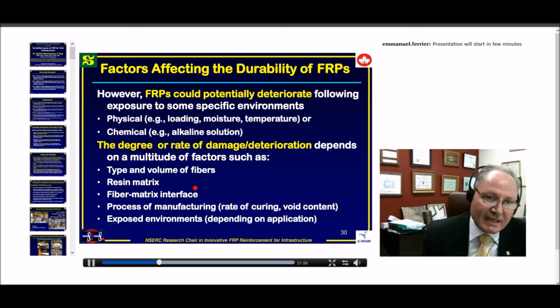I can tell you an example now. I am working on basalt bars during the last few years, and one of the main issues about long-term durability of basalt is really dealing with the fiber matrix interface, because as far as I can see, the industry is still facing the problem with the sizing and finding material which has really good compatibility with the resin. So it's still under research, and one of the key issues to be addressed in the coming years.